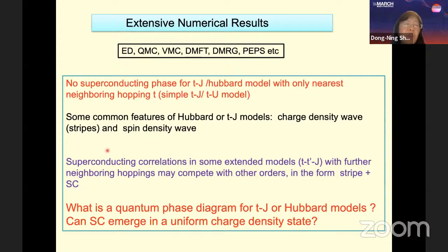There are some common features of Hubbard or TJ models. There is charge density wave and spin density wave, which can compete with other correlations. Then superconducting correlation in some extended model with finite second nearest neighbor hopping can compete with other orders, so superconductivity can also be observed in those parameter regions.